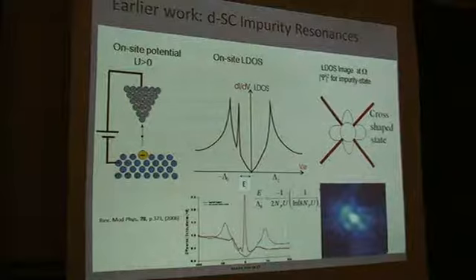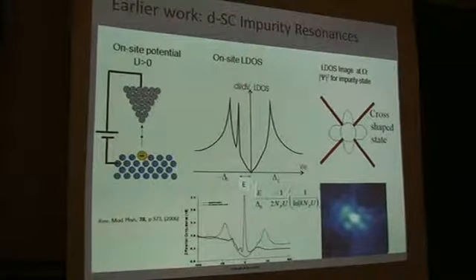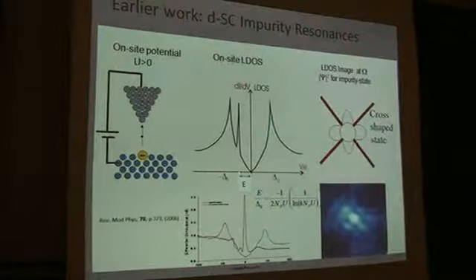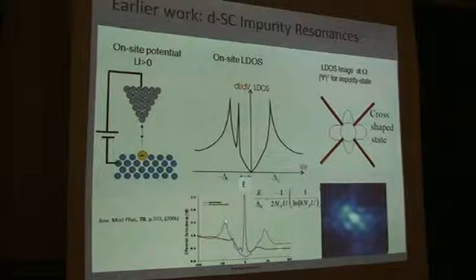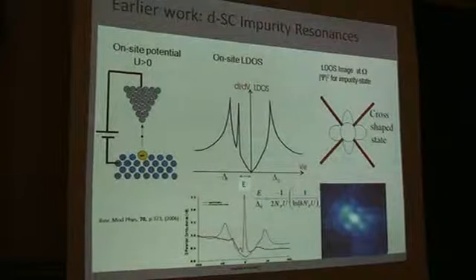Now, they were at the beginning simple theoretical constructs, but it turns out that, like I said, if you have the right glasses, you can see them. So here is the case of the local STM measurement. I'm not going to describe what STM is, just a local tunneling conductance probe that is very precise in terms of lateral resolution, up to the angstrom scale. What you see is that locally it produces impurity-induced resonances. This red line is the tunneling right on the impurity site, and the blue line is tunneling away from the impurity site, somewhere out here. So this is number one.